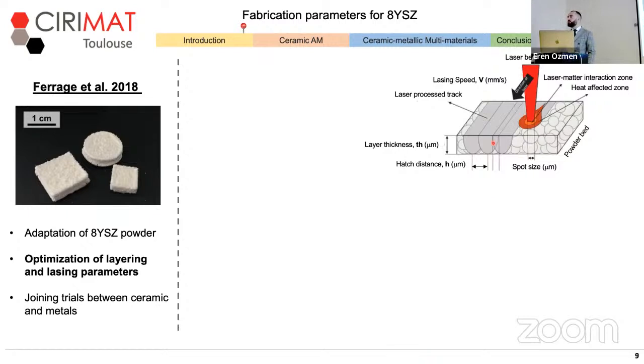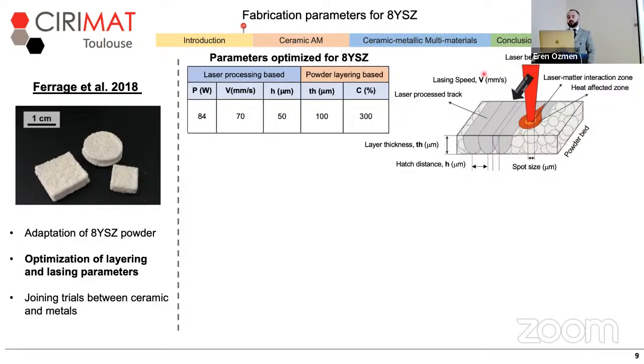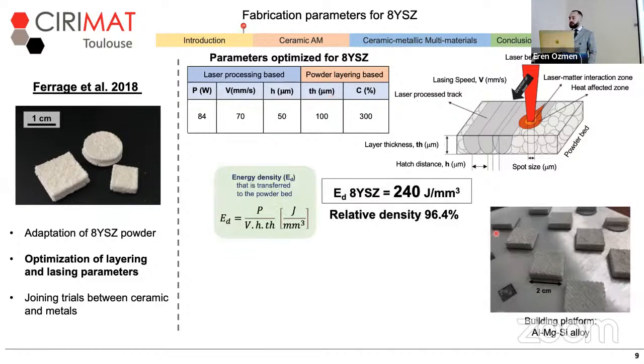laser-matter interaction parameters also needed to be fixed. Parameters such as laser power, lasing speed, layer thickness, and hatch distance, which is the distance between 2 parallel lasing tracks, were fixed after optimization processes. And solid, self-standing 8YSZ pieces, visually corresponding to design data, were possible to fabricate with an energy density of 240 joule per cubic millimeter.